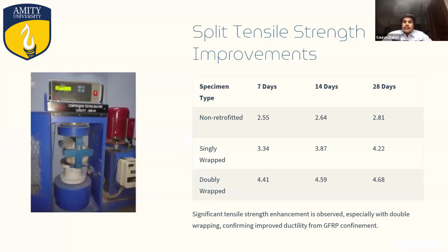Now, talking about the split tensile strength improvements. Here we observe more significant results. The non-retrofitted specimen achieved 2.81 MPa, while the doubly wrapped specimen reached 4.68 MPa. That's nearly a 67% increase. This confirms that GFRP enhances ductility and resistance to tensile cracks, crucial for earthquake zones.